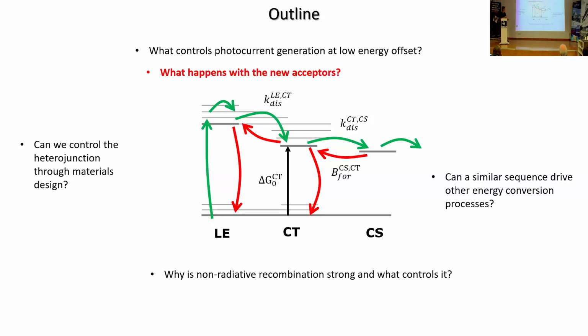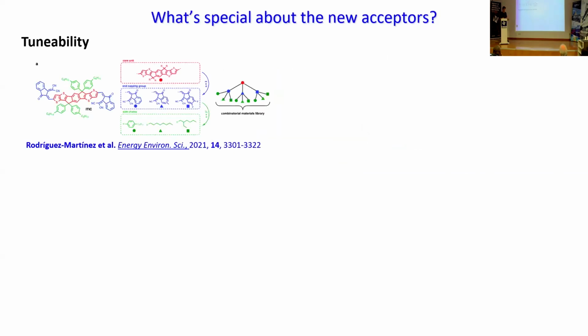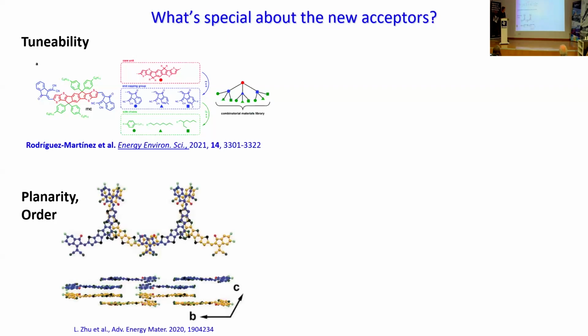So I commented that the efficiencies had been increasing rapidly recently because of using a variety of new acceptor materials that were introduced. And these are really a set of, probably a chemist would call them oligomeric molecular materials, relatively high molecular weight. And there's a wide variety of them, of course, because different building blocks can give you different properties. And the ones that work well in solar cells tend to be flat, and that allows them to pack rather efficiently.